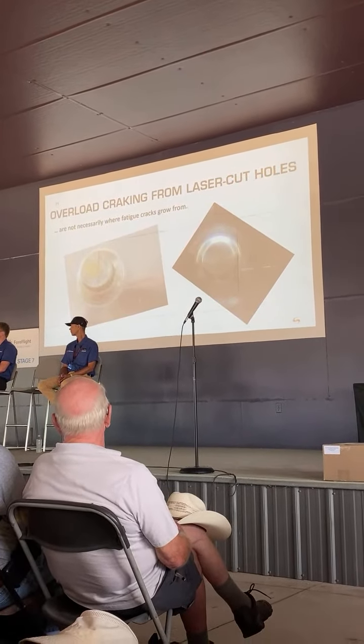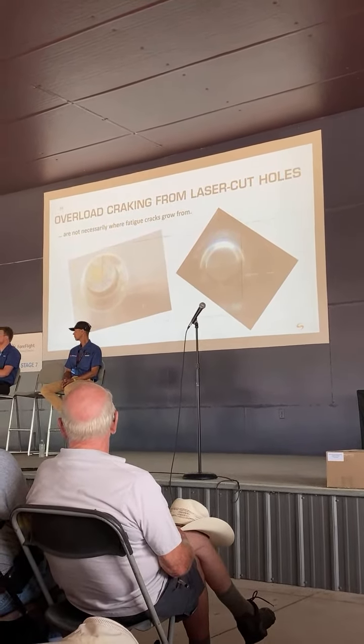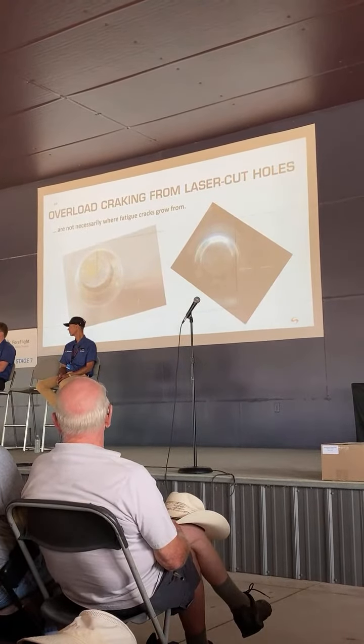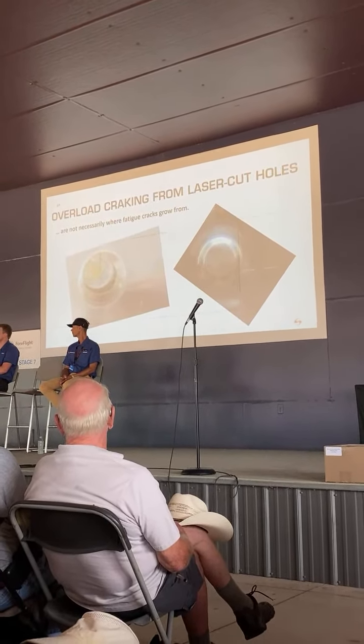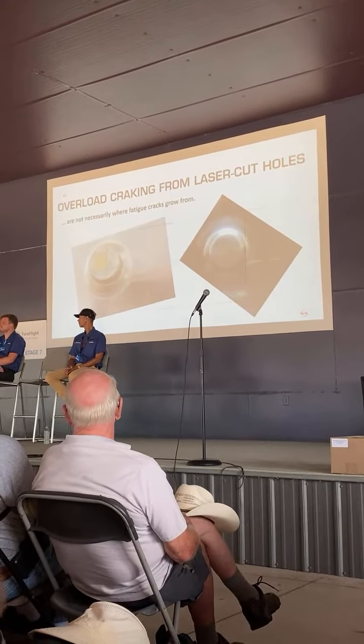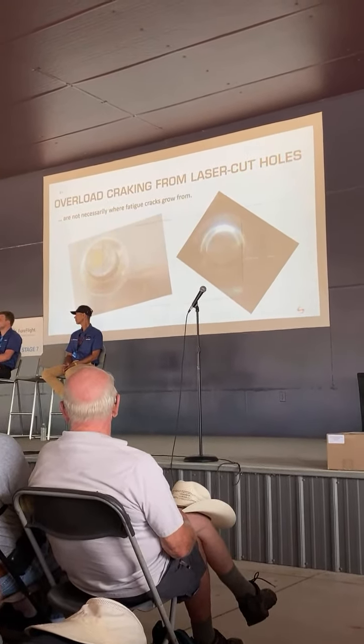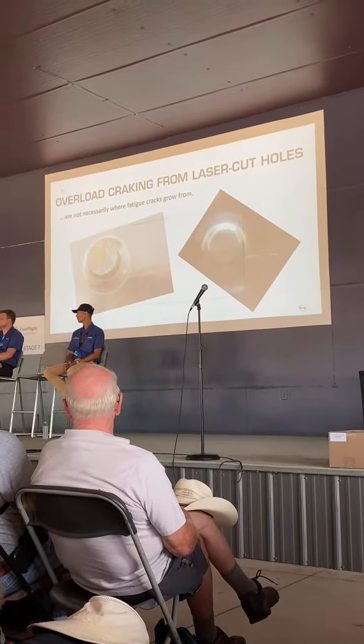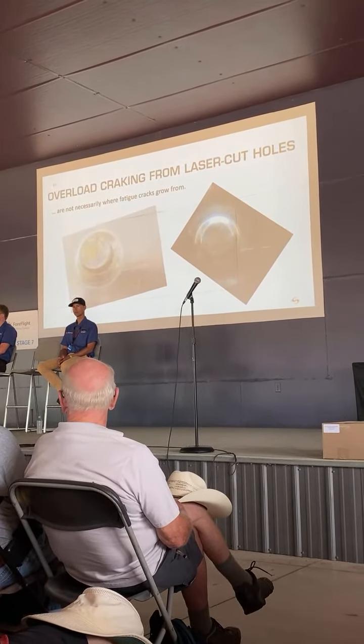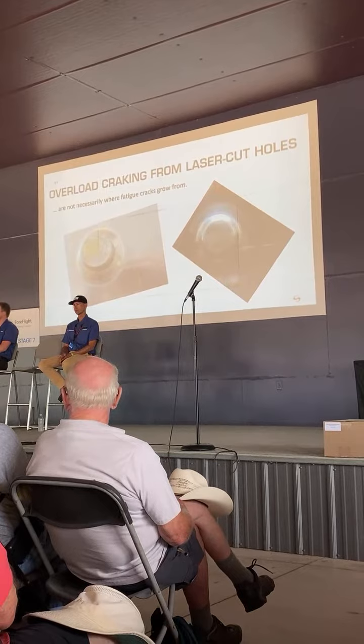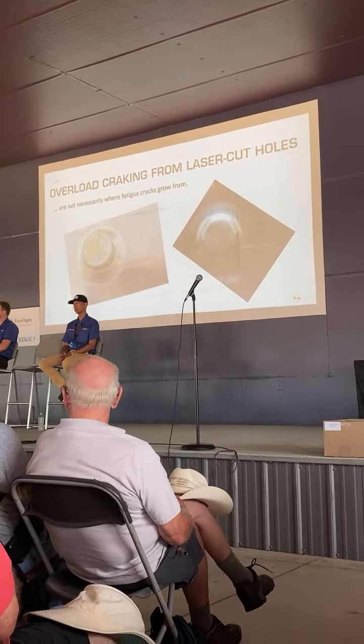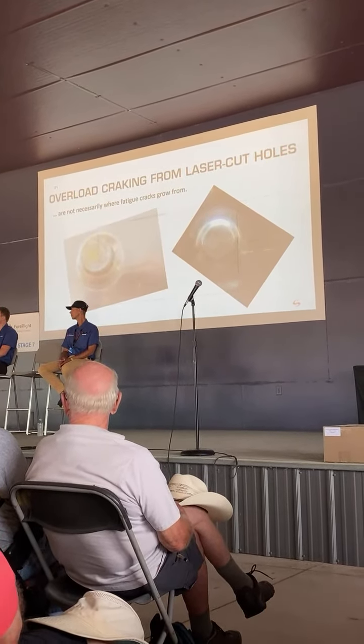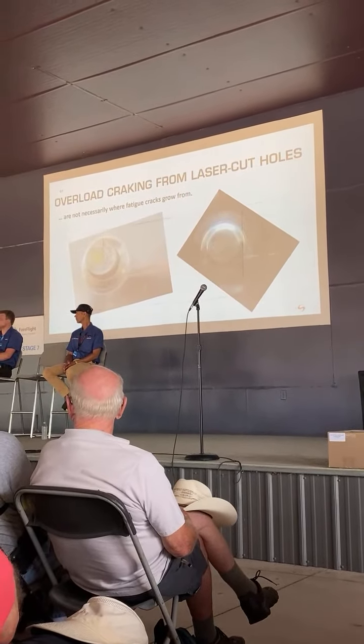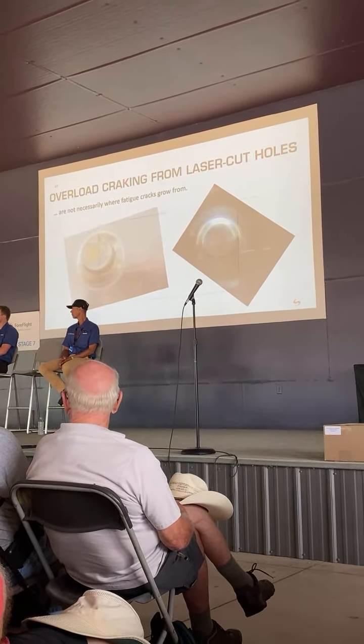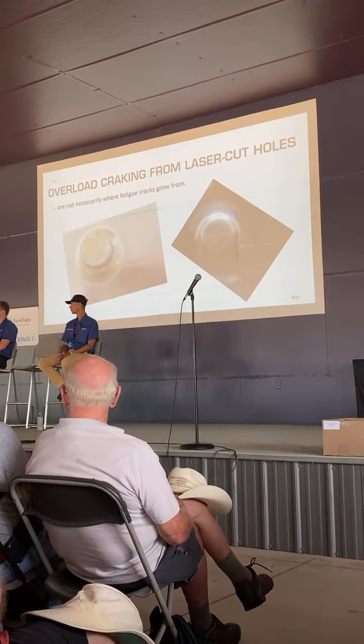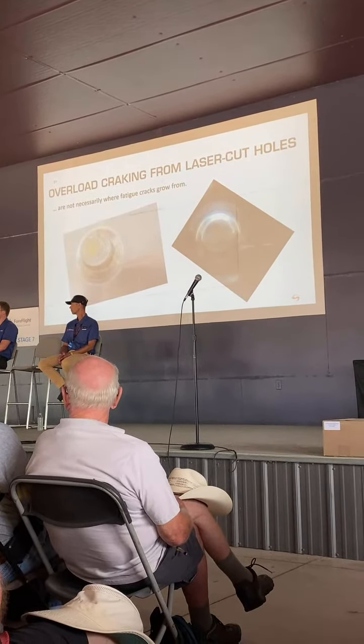That's also why we went to a third party, and we may also pull in others as well. One thing that we have done is look at the overload feature under a scanning electron microscope, SEM. And it's apparent that at the end of the crack, when it's opened up, we flex that crack open and then it closes up. And what that leaves is a stretched, formed portion at the end of the crack that has compressive residual stresses at it.